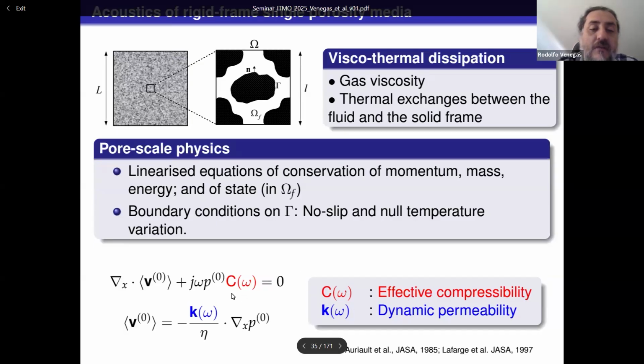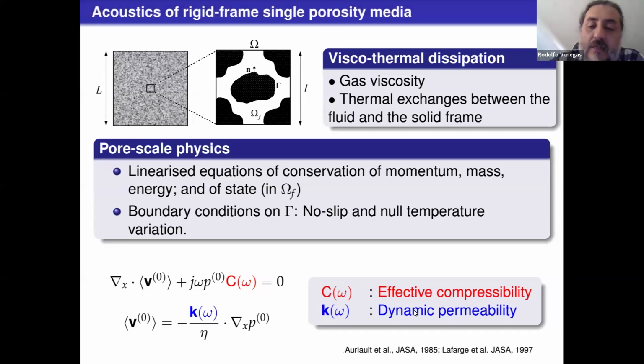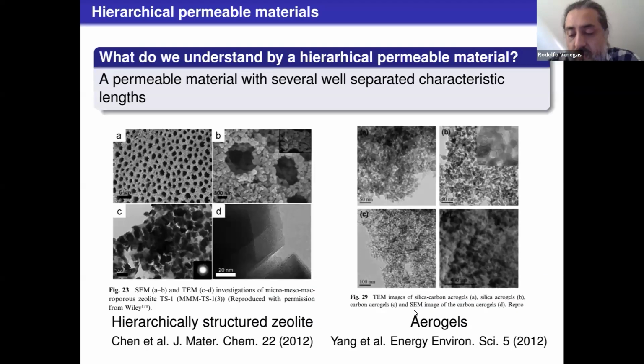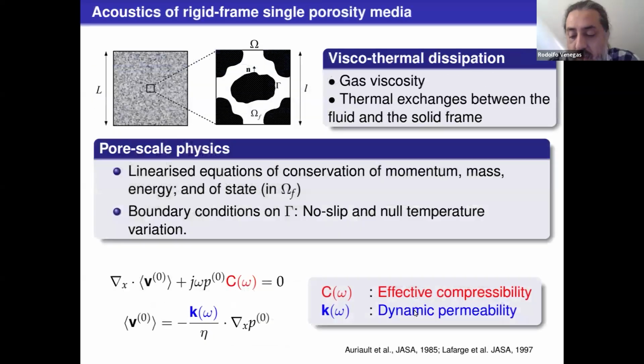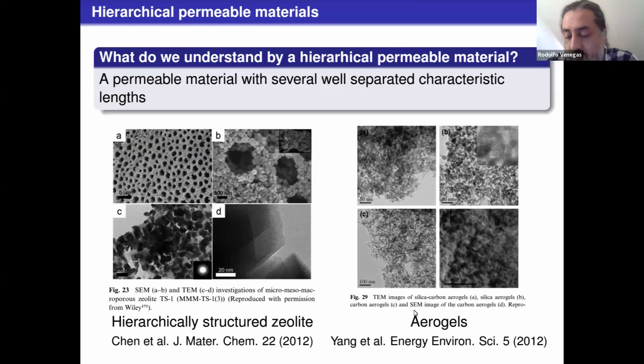We apply homogenization and we get this effective fluid description, where this is an effective mass balance equation and this is the fluid flow constitutive law. These two parameters are the effective parameters of the medium: the effective compressibility and dynamic permeability. We can then relate the dynamic permeability to what is normally called dynamic density, as we will see later. Though this is well known, the question is, what can we do to change this or get different properties of these effective parameters?